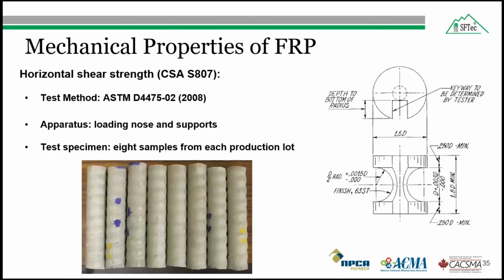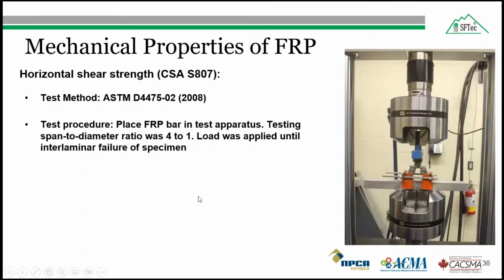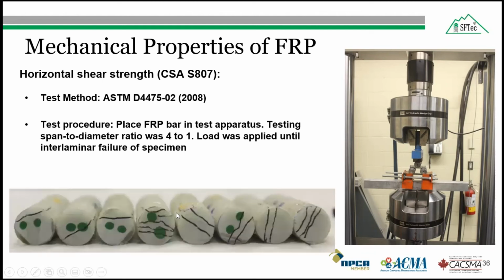The surface of this groove was free of any sharp edges. Here, for each production lot, 8 samples were tested, and all the specimens were cut to 6 times the diameter of the tested FRP bar. So the test specimen was placed at the center of the test apparatus, and the span to diameter ratio was 4:1, and load was applied at a specified displacement rate until the interlaminar degradation of the fiber reinforced polymer bar occurred, as shown in this figure. You can see these are the interlaminar degradations of the bars.